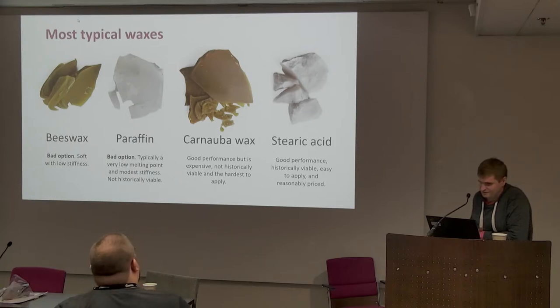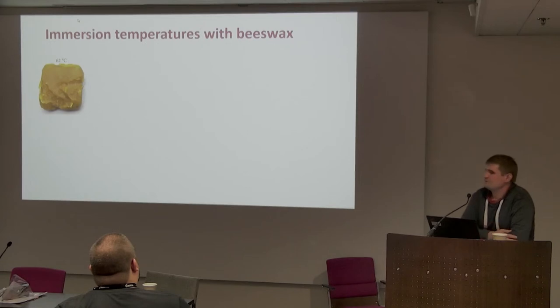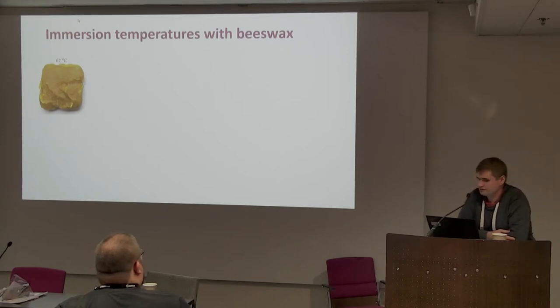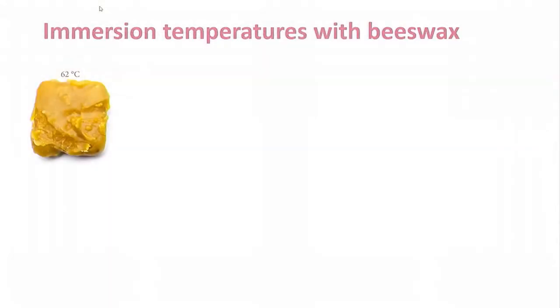Immersion temperature. I mentioned that when we have thoroughly wet leather, the shrinkage temperature is something like 75. But this is not true with dry leathers. So when we do wax hardening, we have dry leather. Here are some comparable pictures of samples I made with different beeswax temperatures.